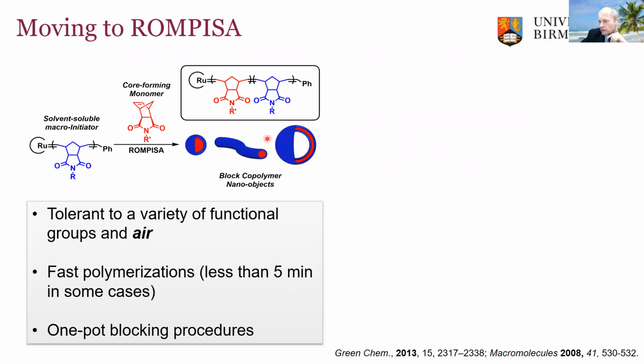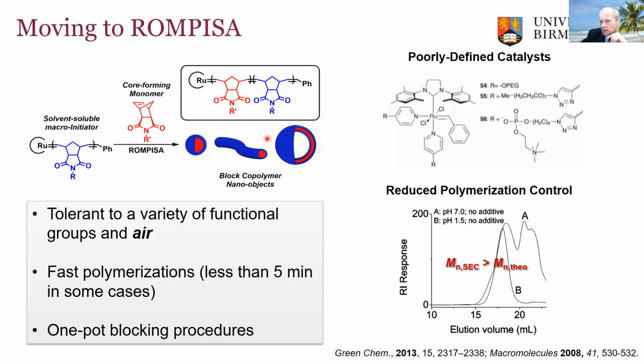We were very keen to do this in aqueous media, which is actually quite challenging. Doing ROMP in water is rather difficult. You either need to use a poorly defined catalyst, or it can be very difficult to get good polymerization control, and you often see quite poor polymerization control. So one of the first things we needed to do was to try and think about a method that may allow us to more readily perform these ROMP PISA reactions in aqueous media without the need for complicated catalyst synthesis.